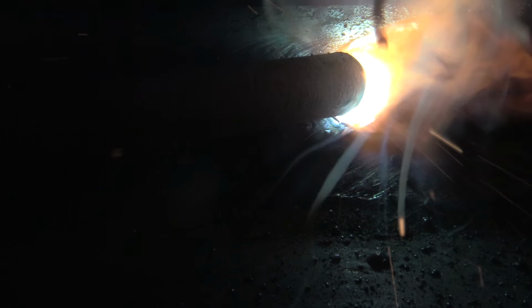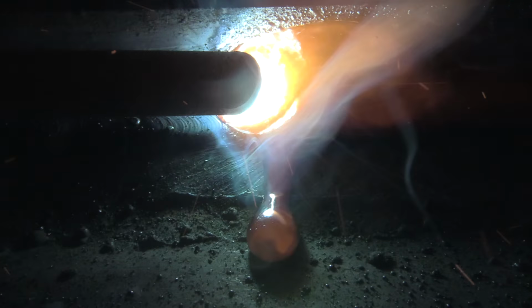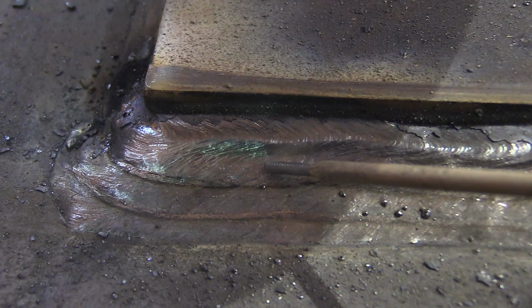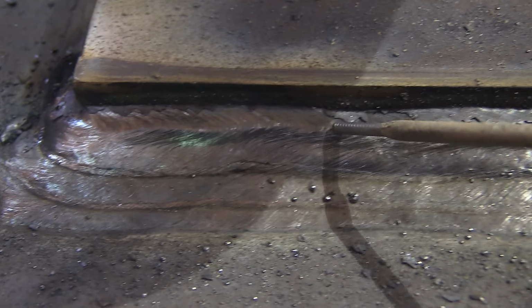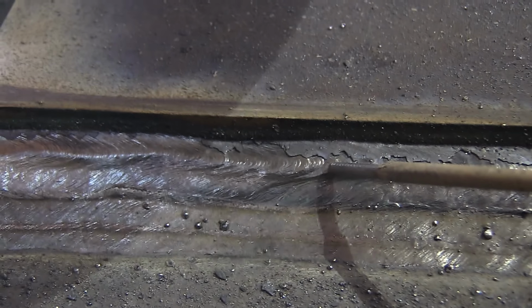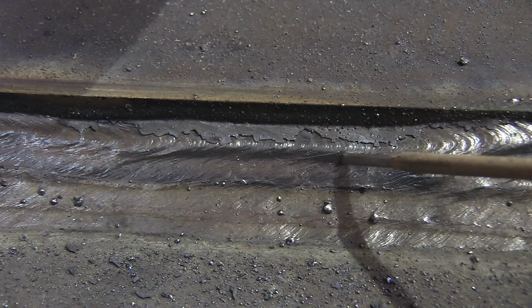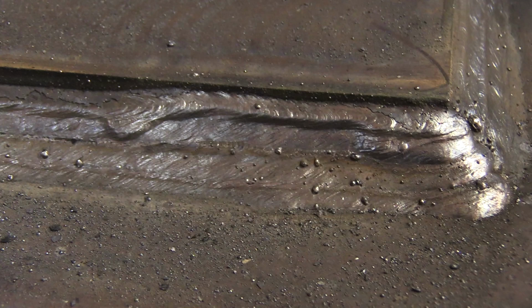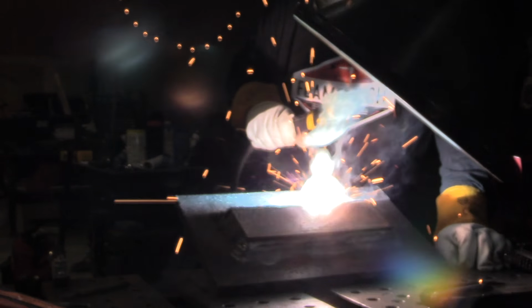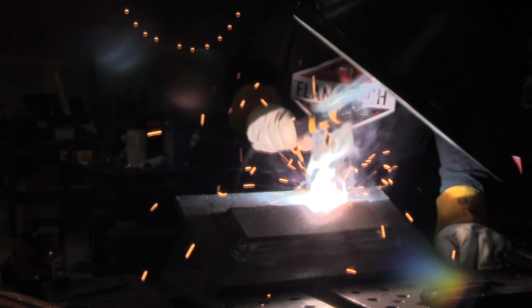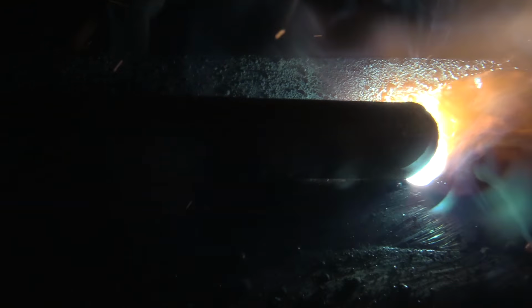And here comes some problems on this third bead. I'm trying to angle it more straight in there, but right about here that it just drips. And there's going to be more problems than that. Not only does the slag drip sometimes, but sometimes it creates this really strange ridge. It looks as if there were two beads there where there was only one run, and I didn't notice this really going on as the puddle was solidifying, but it looks like there were actually two separate beads run there, especially right here. And there weren't two, there was just one big bead, so I tilted it up like this to be more like a flat position, a 1F position, and then ran into another little issue.